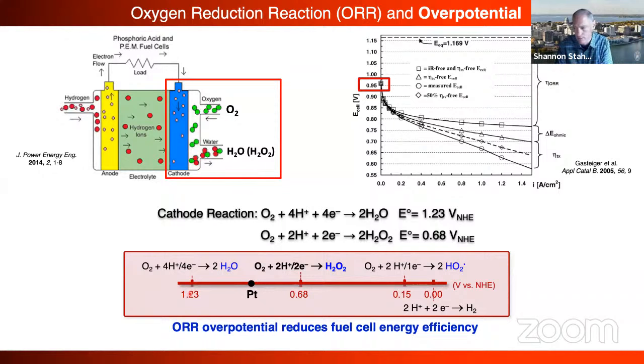And that's just not possible because the kinetic barriers associated with O2 reduction are such that you need a catalyst. That's perhaps obvious, but these catalysts have kinetic barriers that prevent you from operating at the thermodynamic potential. So you just cannot operate efficiently. There's no net current that you can pass if you would poise your fuel cell cathode at 1.23 volts. And so that would be akin to being up here on this plot. So this is a polarization curve for a practical fuel cell system. And what you find is that on the y-axis, you actually have to move that cathode potential down, and you actually don't start to see any current until you get to about 0.95 volts.